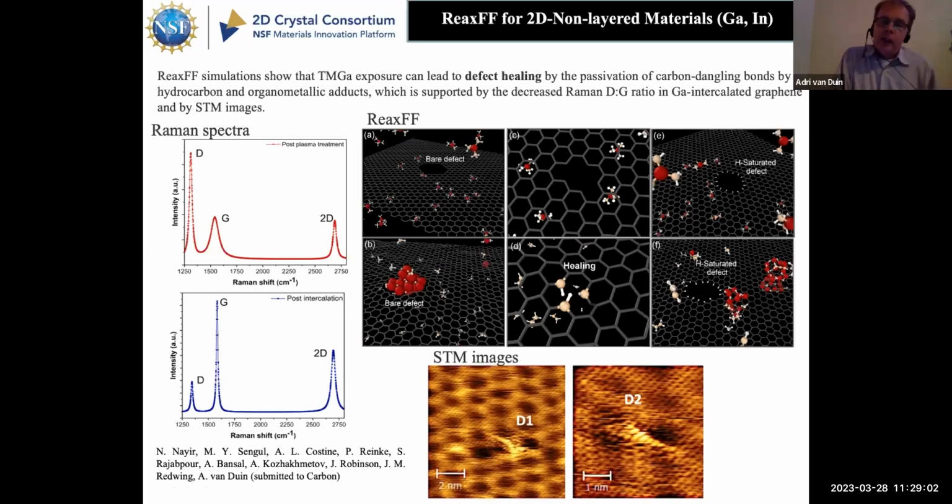Now, it turns out that in principle that synthesis works, but reality is a lot more complex, because these trimethyl gallium species can actually also react with these edges and partially heal them. So sometimes you need to make very substantially large edge defects in the graphene to make this work. If your defects are too small, we see that the defects heal themselves during the gallium metal growth, and eventually the gallium deposition may stop because there are essentially no defects left on the surface.